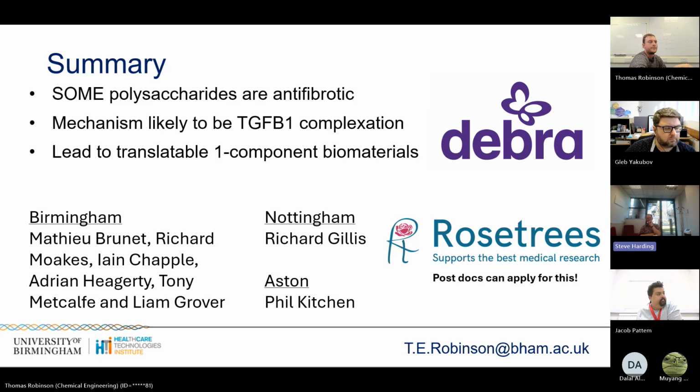Okay, cool. But I was thinking about the spray pattern, and you were saying that at a certain concentration it just became like a splat, right? Yeah. For me, that sounded a bit like C star, where it hits the critical overlap concentration, which you can get rid of by reducing the molecular weight, or at least reduce the impact of it. By reducing the molecular weight, you reduce the viscosity, or intrinsic viscosity. So it's a case of whether you get the same weight-to-weight biological effect from a shorter chain, and this is the trade-off you're going to have.